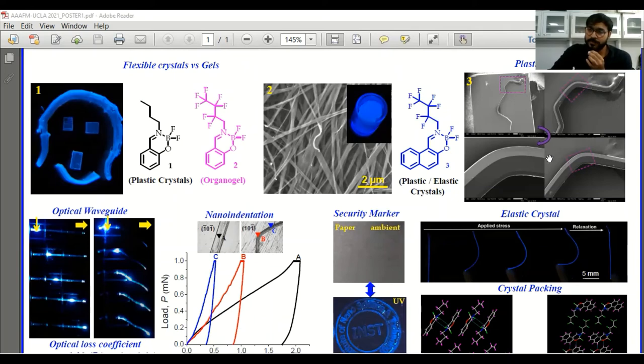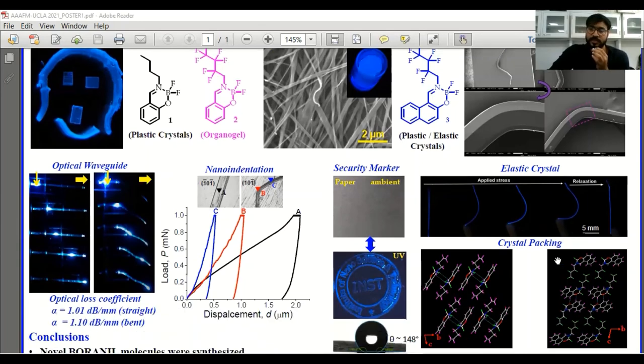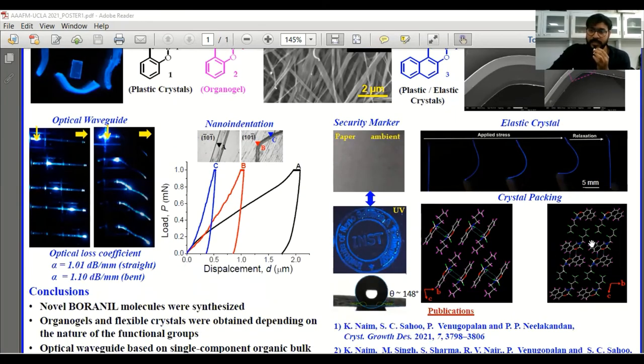The larger crystals show plasticity and the thinner ones are elastic crystals. The crystal packing clearly shows the role of slip planes in generating this flexibility.